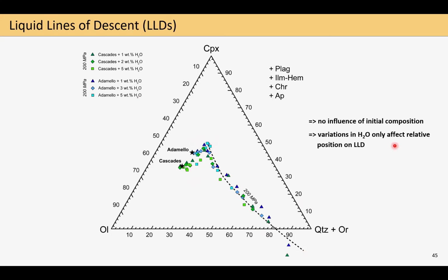However, such a change in water content will only result in a relative shift on the liquid line of descent. So, for example, an Adamello run with a high water content might plot up here, so not a lot of crystallization was going on, but at the same temperature and pressure, a low water run might already be down here, so distinctly more differentiated, just due to a higher crystallization degree.